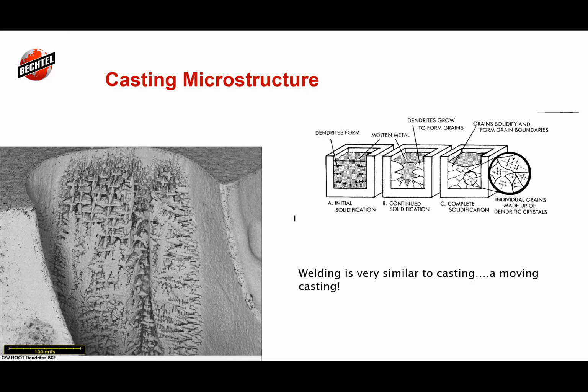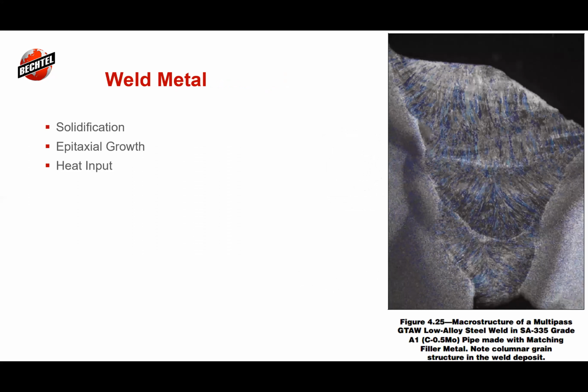And the picture here is a dendritic solidification. The weld metal, as we look, this is a nice picture that shows a multi-pass weld. I think that came out of the welding handbook. It looks like 4 passes maybe. When we see these lines, which show up on my screen as sort of bluish gray, we can see the lines, as you're familiar with when you look at your welds. What we're really looking at is the direction of those grains as they start solidifying.